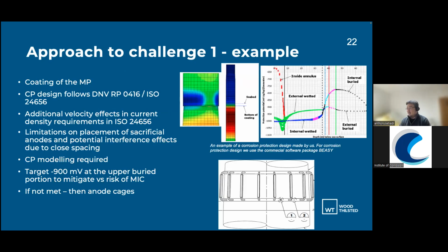For a sacrificial anode system, and even for an ICCP, our approach has been to coat the monopile all the way down to seabed and a little bit further beyond seabed, following DNV RP 0416. ISO 24656 gives you that additional safety factor that you need to consider. As I mentioned before, there are limitations on placement of sacrificial anodes on the structure, so they can only be placed on the transition piece, and potentially using an anode cage, which will then get deployed after the monopile has been installed.